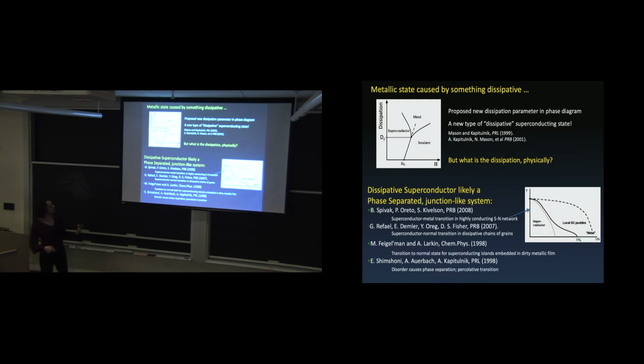Now, there were some theories. And by the end of the day, over many years, they sort of converged on this idea that the dissipation was likely due to phase separation in the system. Right? So even if you think you have a homogeneous 2D superconductor, at some point it breaks up into superconducting and non-superconducting regions. And then this combination of superconductor and metal regions can create a sort of local superconducting puddle network, which can lead to a metal. So it's this puddle behavior.